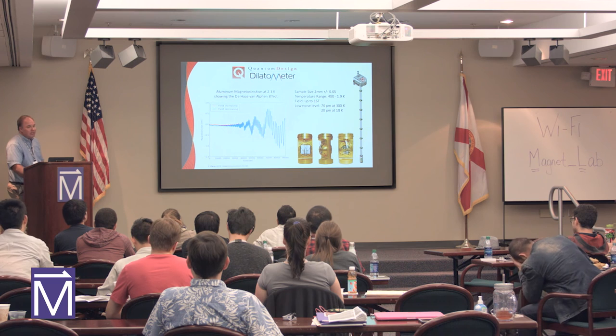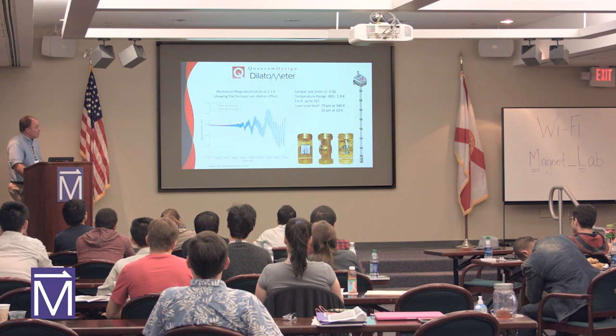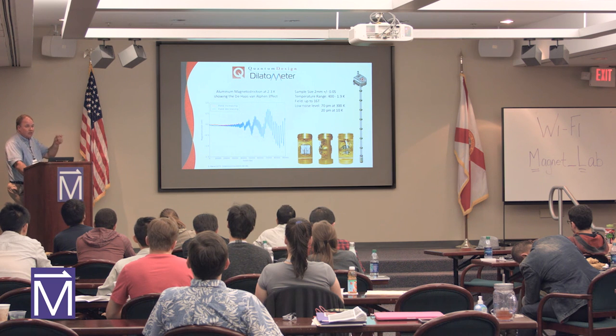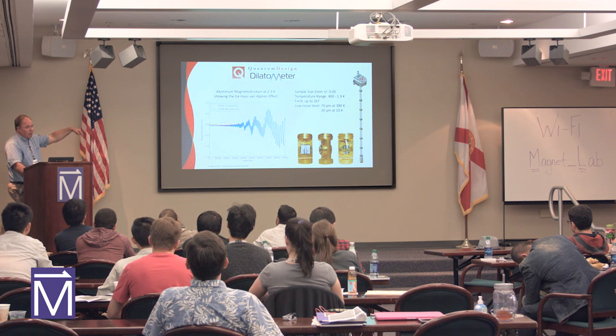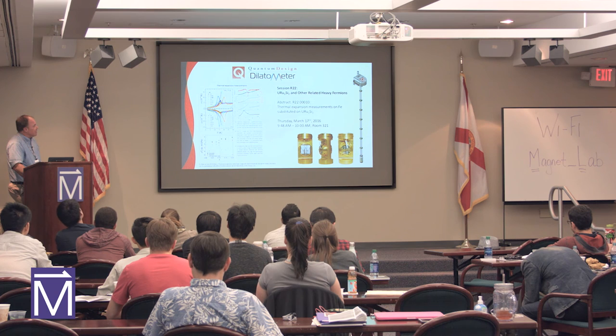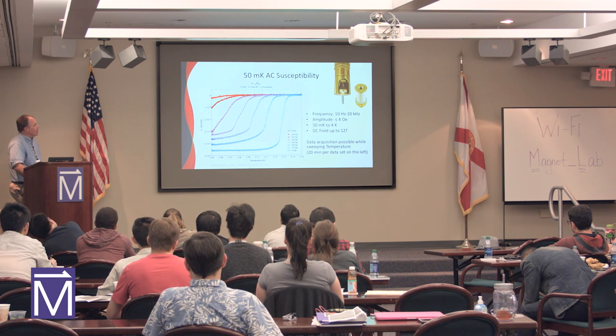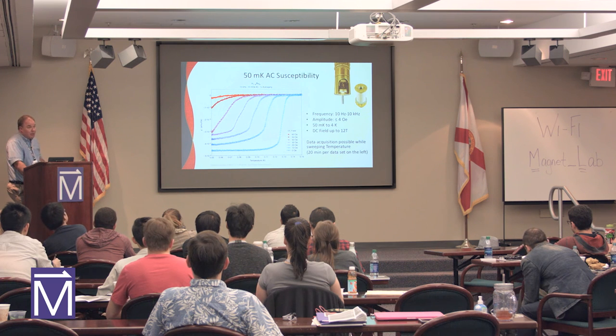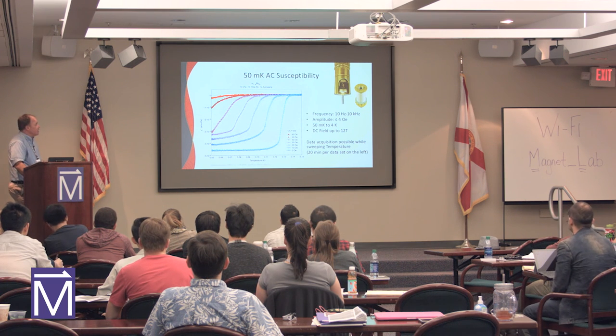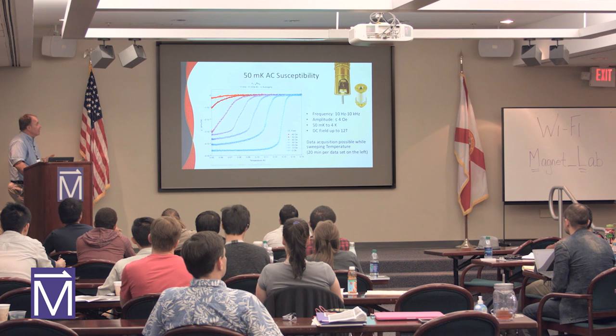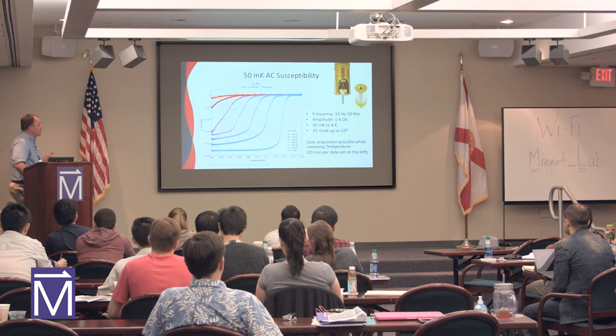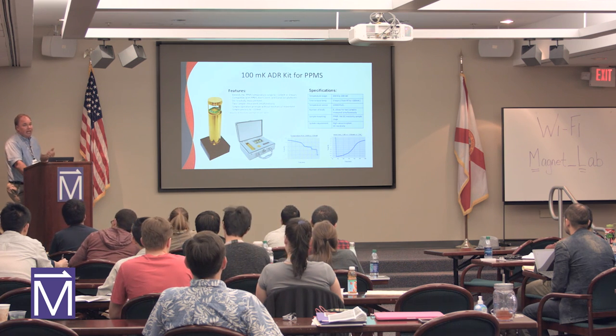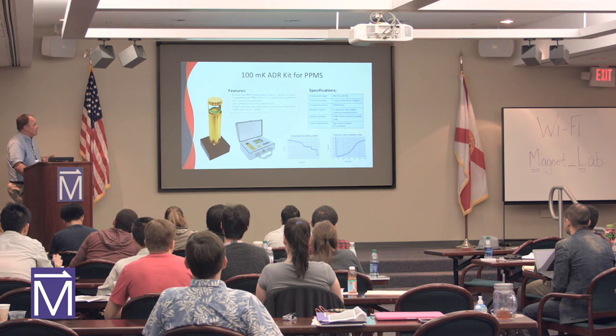What's new at QD? We developed a dilatometer, so you can do the de Haas-van Alphen effect with the thermal expansion, so a new probe that we put in the system to do these things. Some nice papers on this, on a couple of compounds. We have an AC susceptometer for the Dilfridge, so you can do AC susceptibility at 50 millikelvin, not as low as you can do here, but you can add these samples into it. And we added an ADR module to the system, so you can do transport at 100 millikelvin.